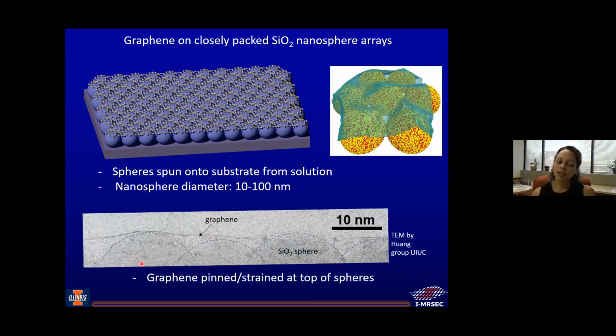Okay. And then here's a measurement that a collaborator, Pinsheng Huang at Illinois, did for us, where she did a cross section. She cut across one of our graphene nanosphere devices and was able to show an image of the nanospheres here, right, with the graphene lying on top of the nanospheres. And so I love this image because it's real. It's rare to see things at this scale; you can see this scale bar here is 10 nanometers. So TEM is an amazing thing. But you can see very clearly that the graphene is pinned to the top of the nanospheres and then relaxed in between, and then pinned and relaxed and pinned and relaxed. And you can see very clearly where this strain array comes from in a very physical way.